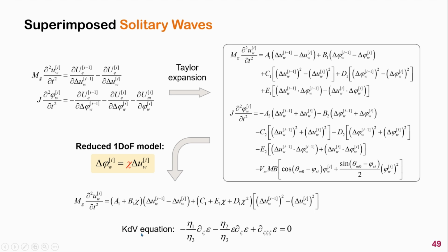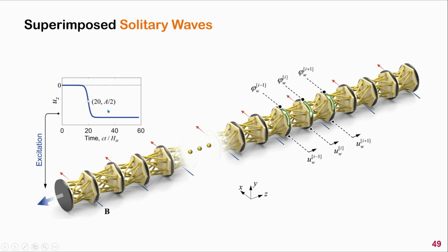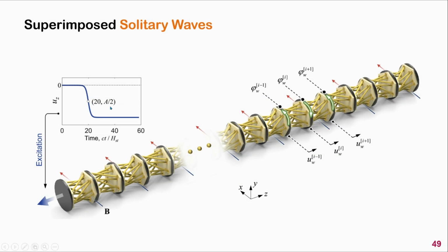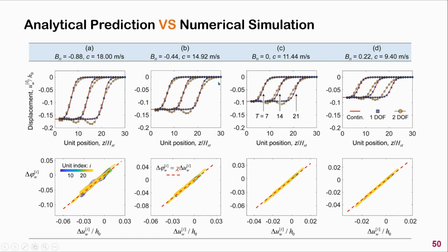This is the finally obtained equation of motion, and we built the continuum model corresponding to the discrete equation of motion. The KdV equation has a solitary solution depending on the coefficients eta 1, eta 2, and eta 3. To examine the continuum model, we solve the initial discrete equation of motion directly using numerical tools, and the analytically predicted solitary solution is applied as excitation to the system. As shown here, our analytical predictions agree very well with the numerical simulation.